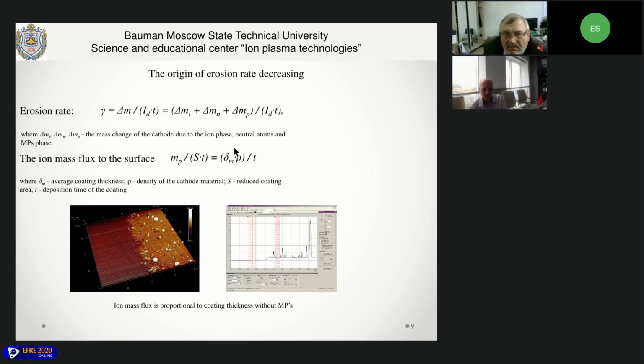So the ion mass flux to the surface can be calculated from very thin coatings. The thickness of these coatings is about 70 nanometers. Here you can see this picture obtained on an atomic force microscope, or maybe a profiler. Here you can see the substrate and these coatings, which consist of flat areas, which are only ion coatings, and these peaks are macroparticles. So when we measure the thickness of the coatings without macroparticles, we can conclude the ion mass flux to the surface.